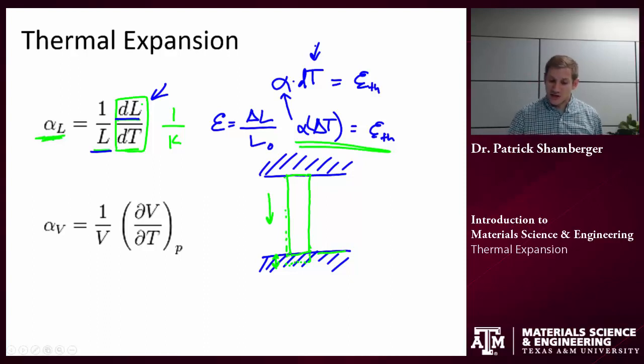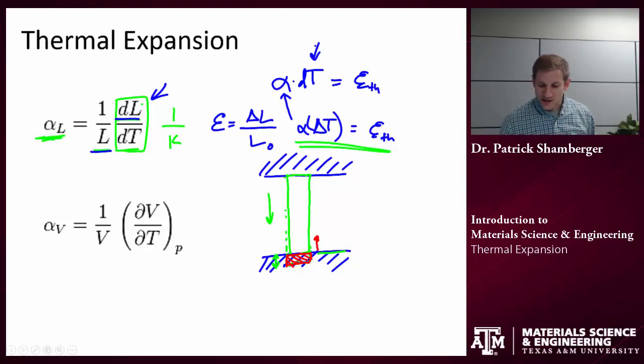However, we know that this barrier is here. What happens is that the barrier is supplying a force and ultimately a stress back on this component. I'm pushing back on the component in the opposite direction so that it retains its original length. The way we would figure that out is we would look at a stress strain curve and say what sort of stress is needed to apply to counteract that thermal strain, because the two strains have to be equal if there's no net change in length. This is why we care about thermal expansion.